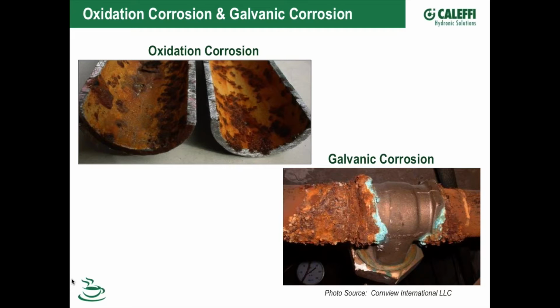So direct metal on metal contact of dissimilar metals, combined with water that is conductive, you can see the effects, and that's usually the telltale sign of galvanic corrosion. You see that oxide, and we've seen that on jobs that we've gone out to, that buildup of oxide on the outside as it's corroded. It looks like it's corroded from the outside, but it's definitely corroded on the inside as well.